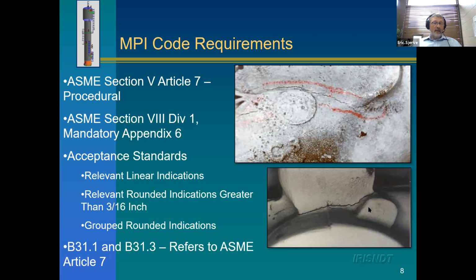And then ASME Section 8 has the acceptance criteria. So like I said earlier, we don't want to be so sensitive that we're calling all kinds of small defects that aren't a problem for fitness for service, but we also don't want to be so insensitive that we're missing big defects that will lead to failure. So Section 8 tells us what is acceptable and what is not once we've done our inspection. And essentially it says that linear indications like cracks are usually rejectable if they're more than a certain length. And rounded indications are rejectable if there's groups of them or they're bigger than 3/16 of an inch. And that would be things like porosity that have come to the surface of the weld and frozen in. And then B31.1 and B31.3 refer back to ASME. So those are the piping codes. They don't have their own procedural part. They refer back to ASME.